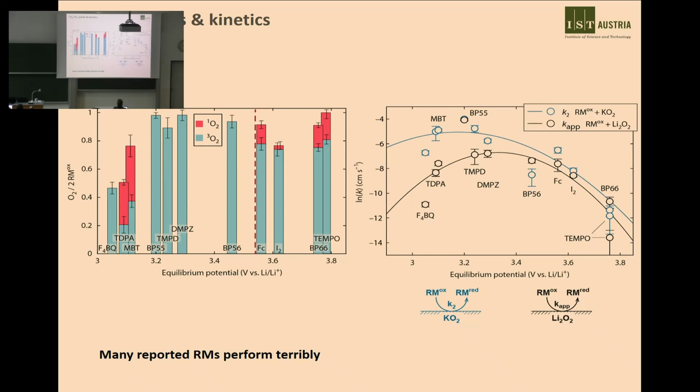So this is the peroxide oxidation in the first step. It's giving this parabola-shaped dependence on driving force. Also for the superoxide oxidation, we get this. The unexpected thing here was that as we go beyond a certain driving force, like here or here, the kinetics goes down. The electrochemists amongst you will recognize here the Marcus inverted region, which was quite astonishing and also exciting to us to see.